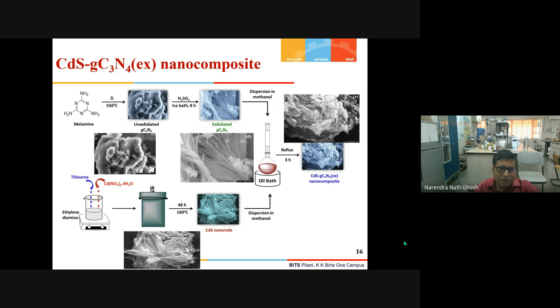In a beaker, we had cadmium nitrate, thiourea and ethylenediamine, and we treated it hydrothermally. We got again some needle-like, nanorod-like structure of cadmium sulfide. We mix it, we reflux it for some time in alcohol, and then we separate it by using an ultracentrifuge, and we got the cadmium sulfide graphitic carbon nitride nanocomposite.